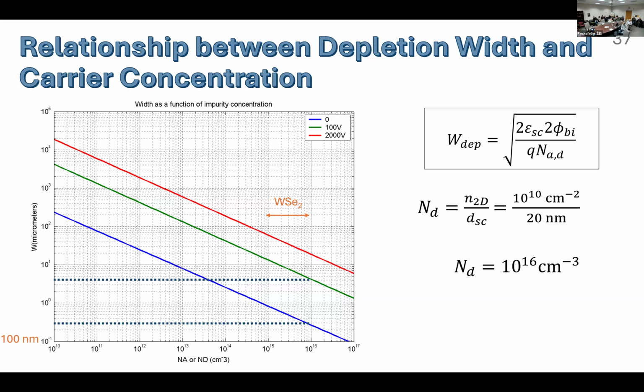The carrier density in 3D is, of course, in electrons per centimeter cubed. But if you recall from my method section, the carrier density that I gave you was in electrons per centimeter squared. So in order to go from centimeter squared to our 3D carrier density, all we have to do is divide by the thickness of our semiconductor. In tungsten diselenide, the typical carrier densities are around 10 to the 10 electrons per centimeter squared. The average thickness of our devices used in this project is around 20 nanometers. So that gives us a carrier density of around 10 to the 16.